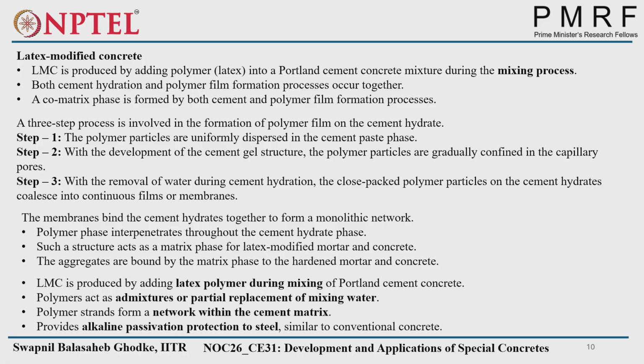So latex modified concrete is produced by adding latex polymer during mixing. Now here you see the new word is coming, that is latex. So we'll see what is the latex. Latex polymer during mixing of Portland cement concrete. Polymer acts here as an admixture or partial replacement of the mixing water. Polymer strands form network within the cement matrix. Here you can see the last sentence, you just now asked about the reinforcement, that it provides alkaline passivation protection to the steel similar to the conventional concrete.